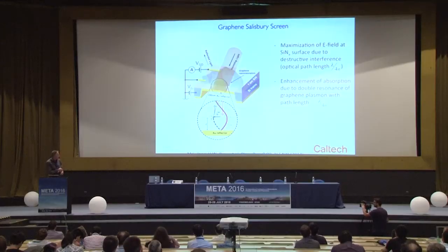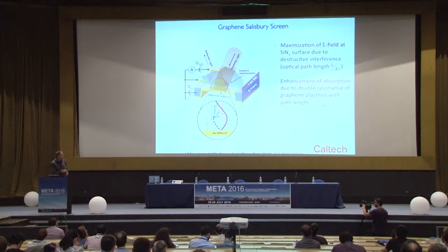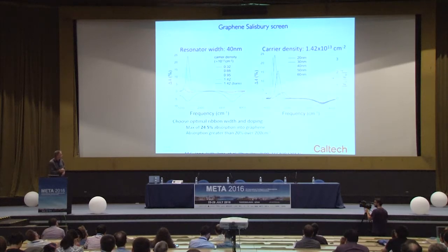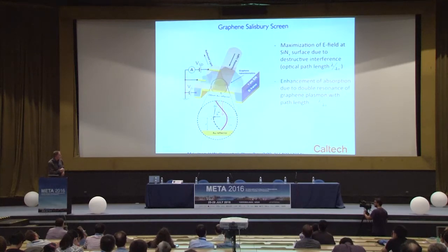And the substrate imparts a pi phase shift, of course, upon reflection, and that leads to an extinction of the reflected beam. And of course, with a back reflector, that leads to a condition for extremely high resonant absorption in this so-called Salisbury screen environment. And as we can tune the carrier density of graphene,